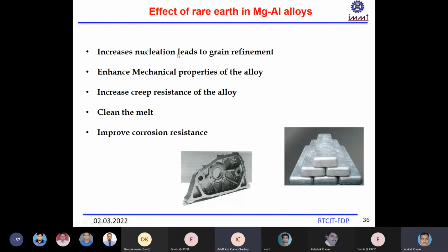So here you can see the effect of the rare earth. Actually, this rare earth element increases the nucleation, and that's why it reduces the grain size, and grain refinement takes place during solidification. When the grain is refined, obviously your mechanical strength will be increased, and it also improves your metal quality and reduces the impurity level. So the creep strength of this alloy is also increased, because the intermetallic which is forming is stable at high temperature. Rare earth also improves the corrosion strength. So that's why rare earth has a very good effect in magnesium aluminum alloys.